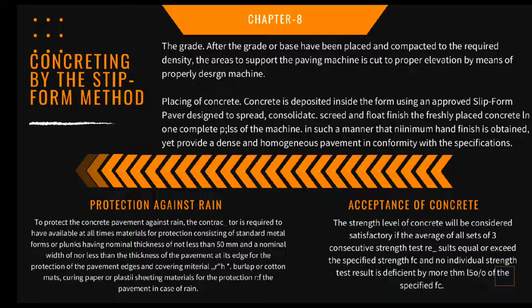The sliding forms are rigidly held together laterally to prevent them from spreading. The forms are trailing behind the paver, such that no appreciable slumping of the concrete will occur and the necessary final finishing can be accomplished while the concrete is still within the forms. Any edge slump of the pavement, exclusive of edge rounding, in excess of 6 mm is corrected before the concrete hardens. The concrete is held at a uniform consistency, having a slump not more than 40 mm.